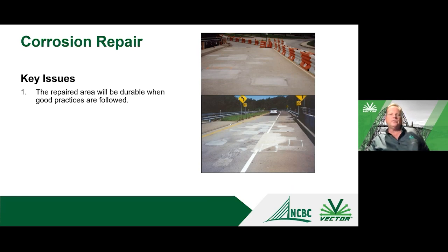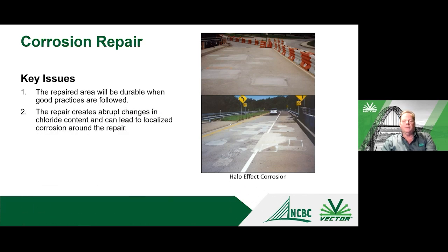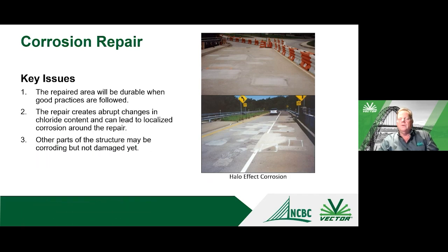So like I said before, if you follow the procedures, the repair areas themselves will be very durable, and will address the corrosion of the repair. Now, this is where we start thinking about the repairs being just part of the overall structure. The repair is going to be durable, but you see here on the bottom right a photo that I took many years ago in the Northeast, where you see generations of repair, and you're chasing the corrosion issue around the structure, and you see new areas that are marked out. And so more repair, and eventually that deck is going to need to be replaced at this rate.